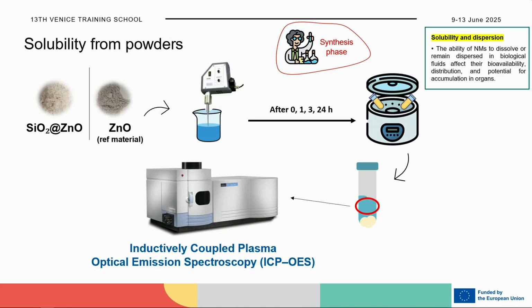Then we look also at the solubility of our material, since we have this core-shell structure that is silica dioxide coated with the zinc oxide. So in this case, we again use zinc oxide as reference material. So we prepare our dispersion. Then after different time points, according to the toxicity testings, we look at the supernatant after some time.